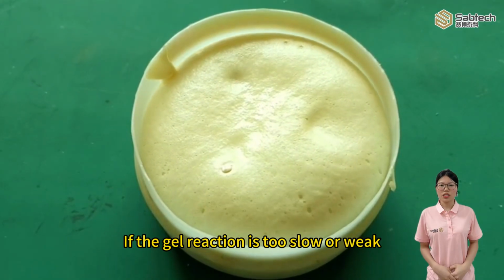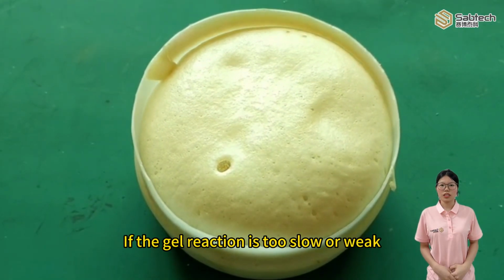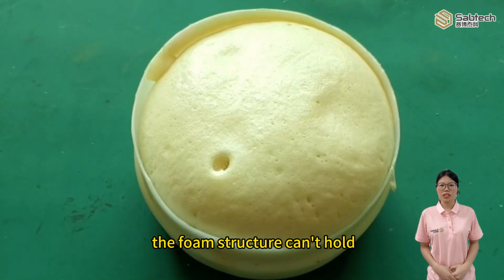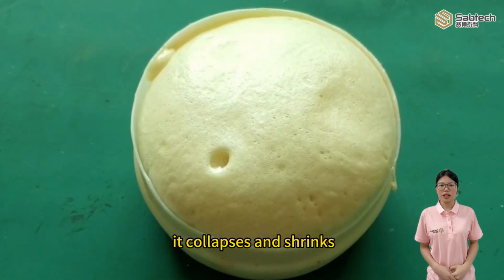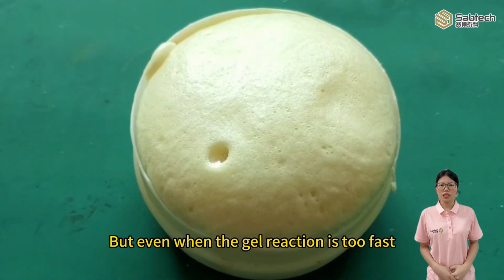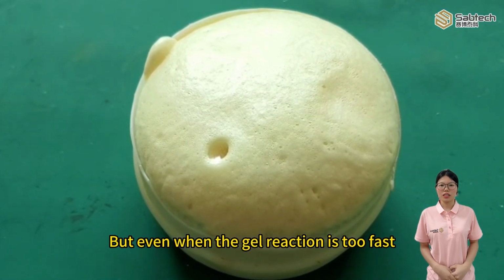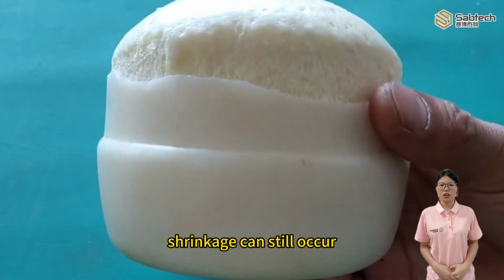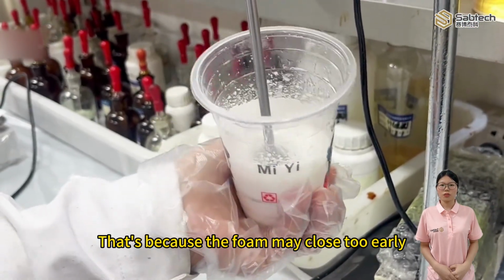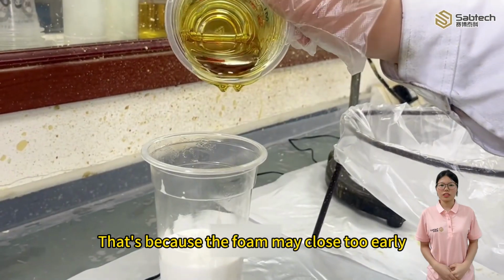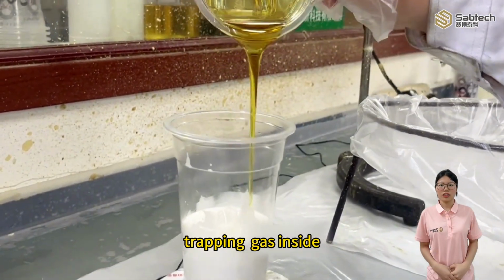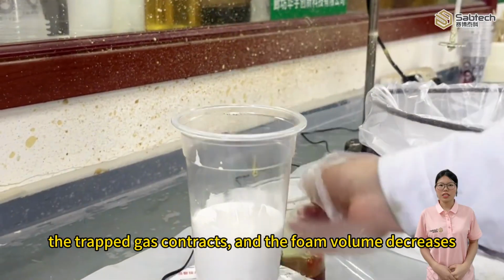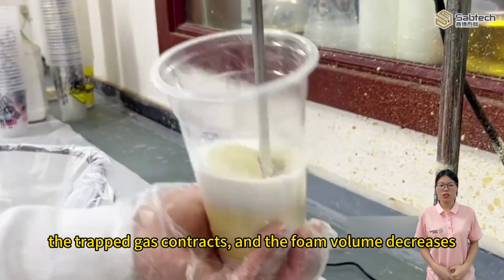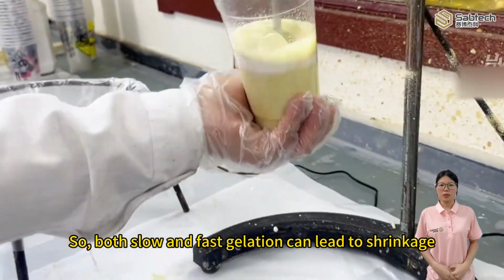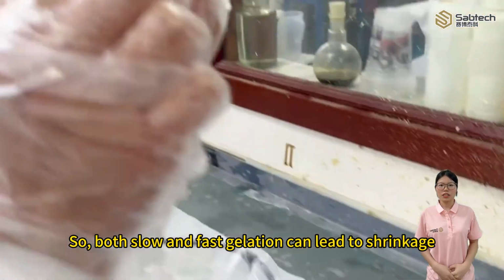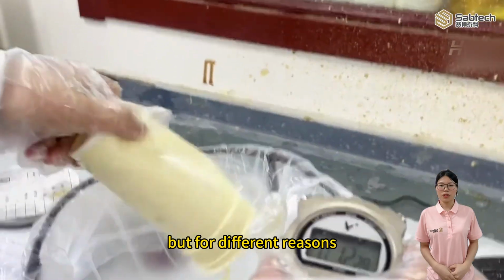If the gel reaction is too slow, the foam structure can't hold, is collapsing and shrinkage. But even when the gel reaction is too fast, shrinkage can still occur. That's because the foam may close too early, trapping gas inside. When cooling down, the trapped gas contracts and the foam volume decreases. So, both slow and fast gel reaction can lead to shrinkage, but for different reasons.